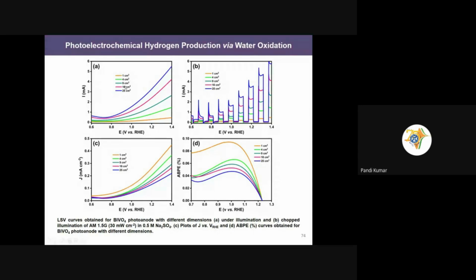Then what I did, I converted all the current into current density. When we see this, the pattern is totally reversed. Why? Obviously this 4 centimeter square produces more hydrogen than the 1 centimeter square, but 1 centimeter square produces 100, so this one has to produce 400, but it produces 150 or something. When we converted it to current density, the trend was totally reversed. That means some losses are there. If it produces 150 hydrogen, then 250 hydrogen is lost. So we have to fix it.